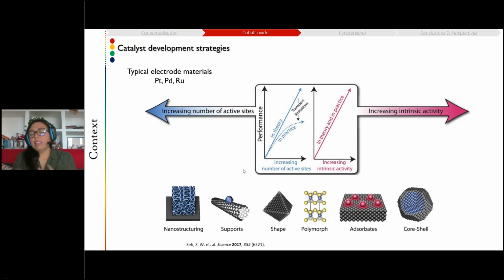And the activity will be related with different aspects, including the structure, the support in which it's used, the shape, the polymorphism that are used, the interaction with the adsorbates or other morphological aspects. And different strategies have been developed to try to increase the performance of these materials, including the increase of the active sites by decreasing the size, so using nanocatalysts, for example. But this also always tends to get to a limiting point where transport limitations are too important to attain the theoretical performance. But then what would be really useful is to increase the intrinsic activity of the material.